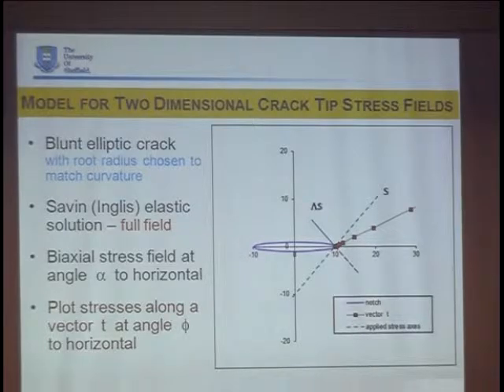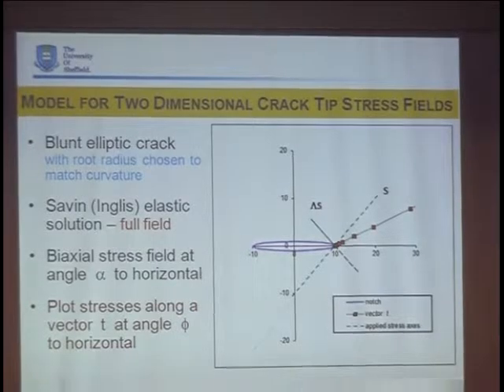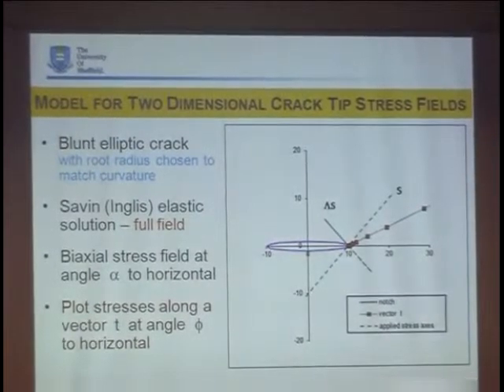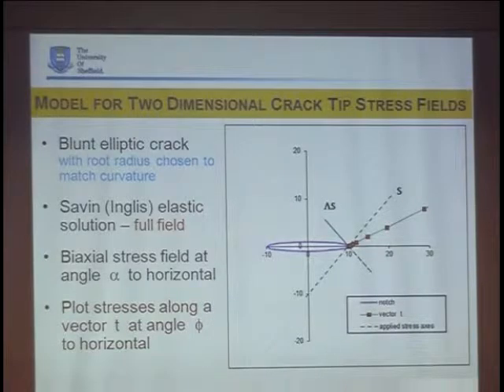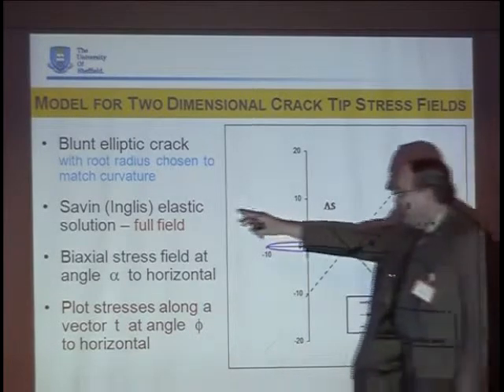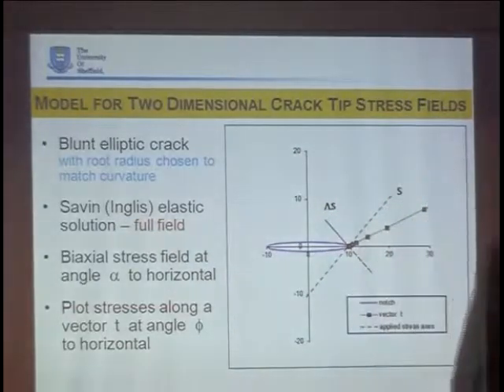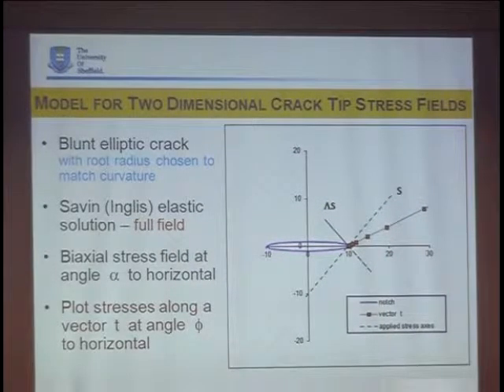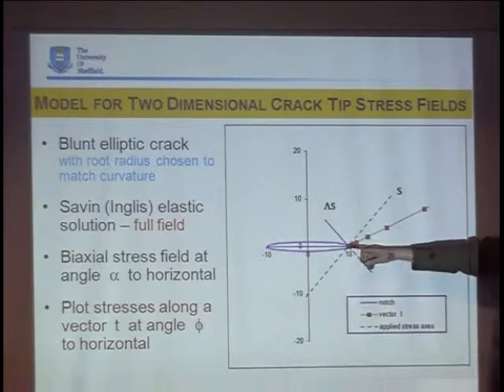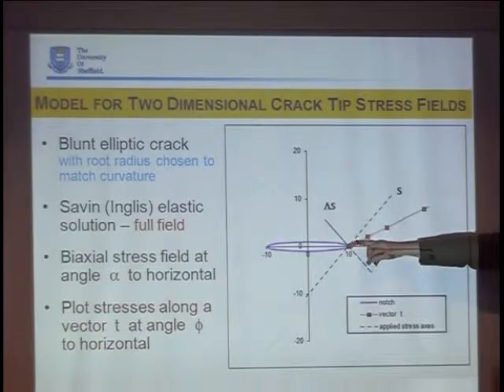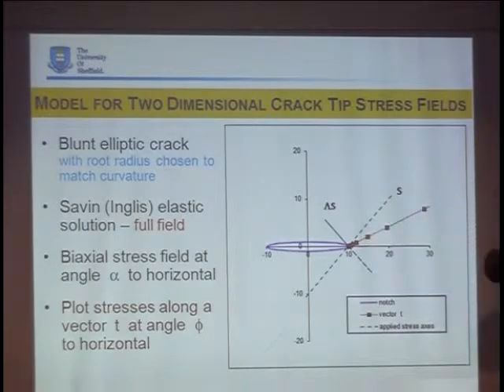Why do we have our problems? Well, this analysis I hope will explain where I got it wrong, because I believe in fracture mechanics basically. So, we've had at least two people mention the Inglis solution, or the Savin solution. We've set that up on a spreadsheet so I could solve it. It's purely an elastic solution for stresses around an elliptical notch, which I have exaggerated here to make the notch narrow. It's very crack-like. And also we can control the radius of curvature of the crack tip, because all real cracks are blunt. There's no such thing as a singular crack.